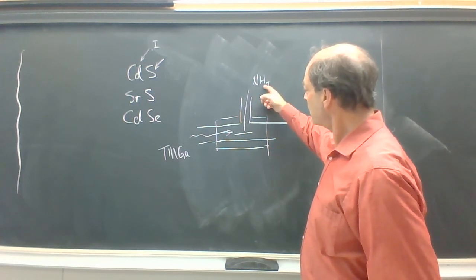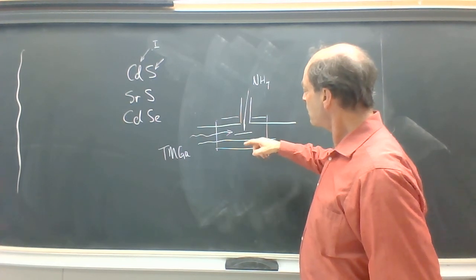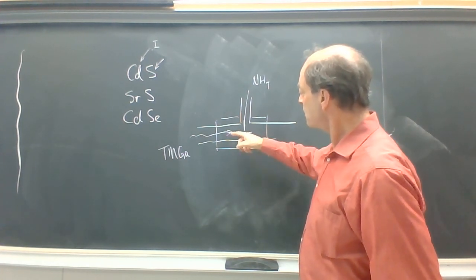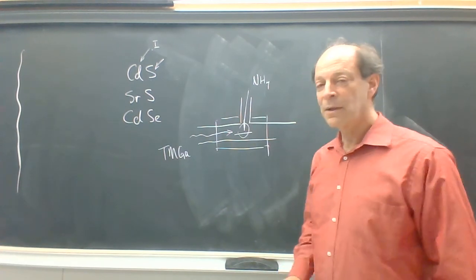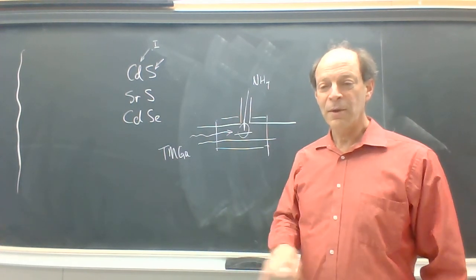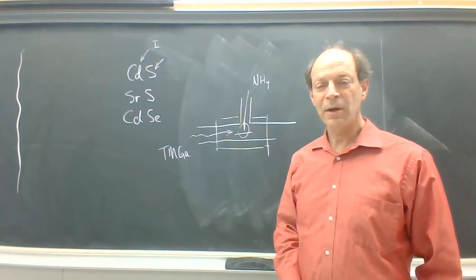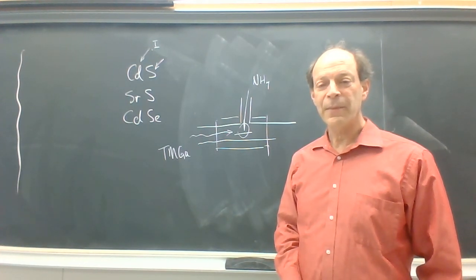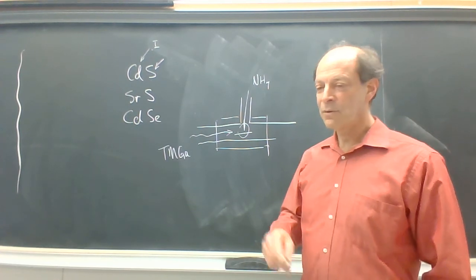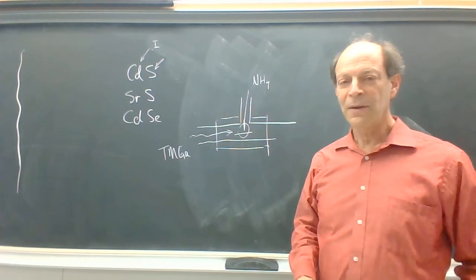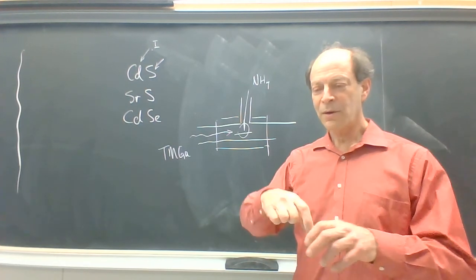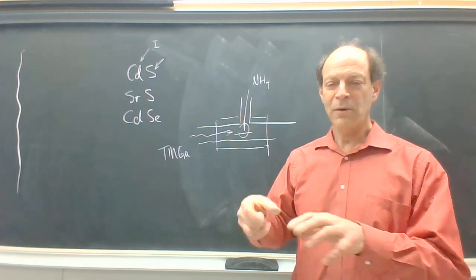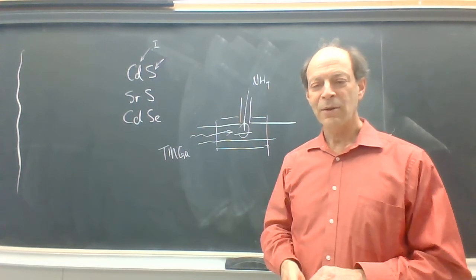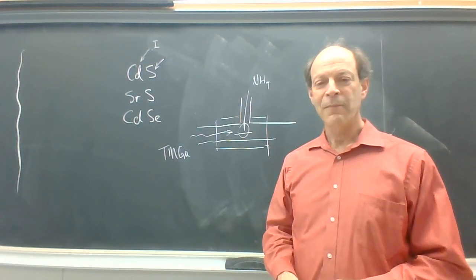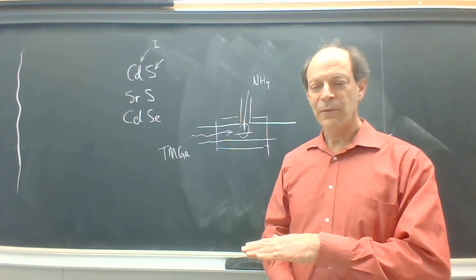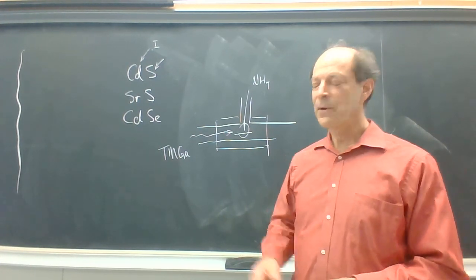So that additional component added to the flow of the TMGa would react at the substrate to grow, for the very first time, smooth uniform films of gallium nitride. Now that was not achieved by anyone else at the time, and it was only because of this unique furnace design that rather than growing weird-looking crystals which were randomly oriented and created a rocky landscape at the micro scale, he was able to grow very smooth, literally atomically smooth layers on the substrate.